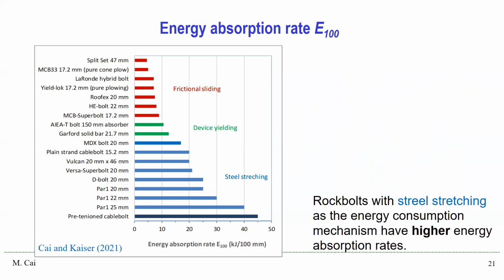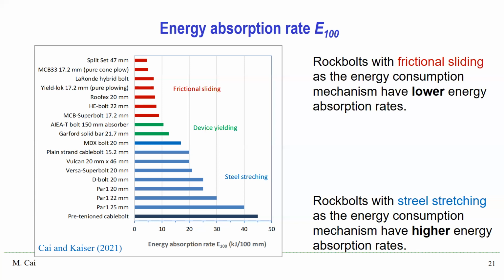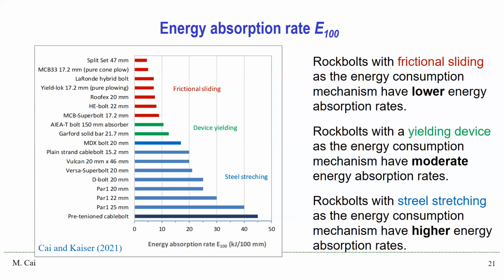For cable bolts made using high carbon steel, the energy absorption rate is the highest when the steel stretching is involved. For rock bolts having frictional sliding as the energy consumption mechanism, the energy absorption rate is low. The energy absorption rate by steel rock contact friction is the lowest. For rock bolts with a yielding device as the energy absorption mechanism, they have a moderate energy absorption rate.